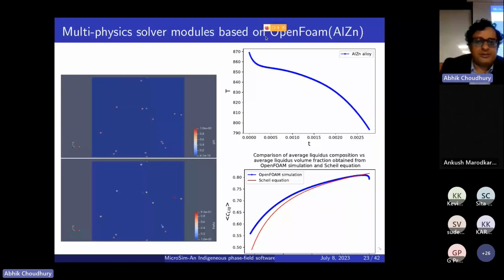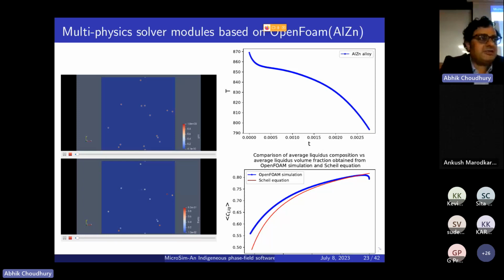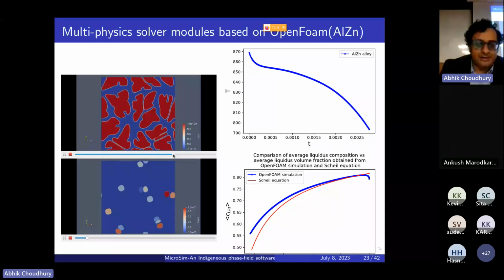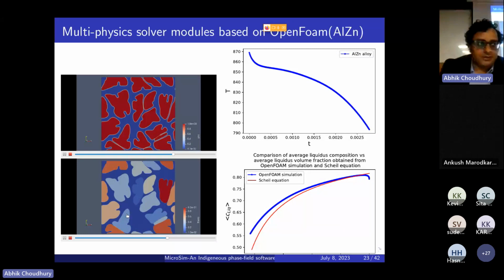This is a part of our multiphysics solver, which is capturing a typical industrial problem, casting. In casting, the typical situation is that you start off with an alloy, you have some nucleation happening, and then there's a cooling procedure by which the system cools and the microstructure evolves. This has been incorporated into our phase field module in the OpenFOAM module that exists, where you see over here multiple dendrites growing with multiple orientations, and as the system evolves to this microstructure, you can extract a cooling curve, which is the temperature versus time curve, as well as the segregation, that is the liquid concentration in the domain as a function of the fraction solid.